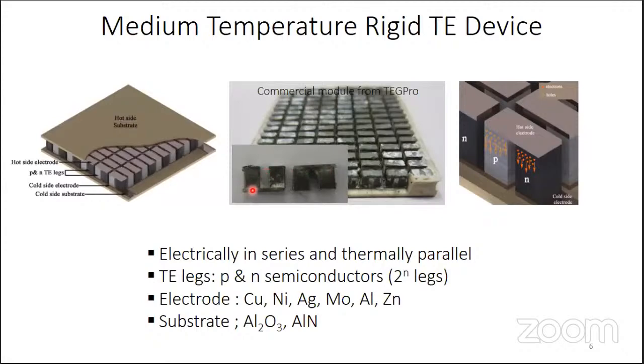How is it connected? It is connected with a very highly electrically conductive pure metallic material. So you will have a semiconductor and metallic material electrical contact. This contact is expected to be stable up to medium temperature, that is 600 degrees, 500 degrees, elevated temperature. It has to be stable thermally, thermophysically, and thermochemically. Then only the full device will work for the intended operating temperature and operational duration. So this is what is challenging. So that is why we are talking of thermal stability.